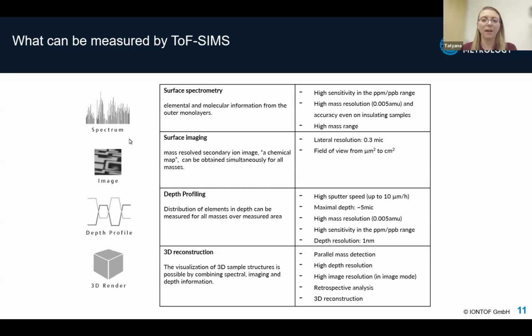Depth profiling combines 1 nanometer depth resolution with sputter rates up to 10 micrometers per hour, while maintaining sensitivity. Finally, 3D reconstruction integrates these capabilities, enabling comprehensive volumetric chemical analysis with full retrospective capabilities. Keeping these properties in mind, let's see the place of ToF-SIMS within other surface-sensitive techniques.